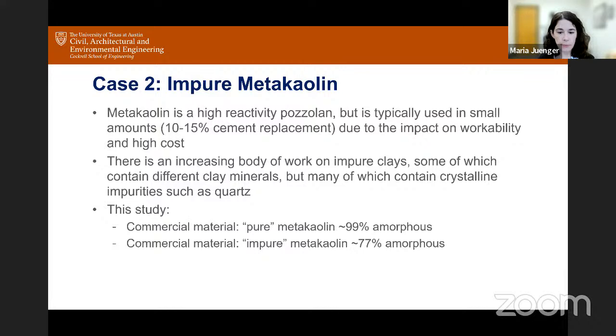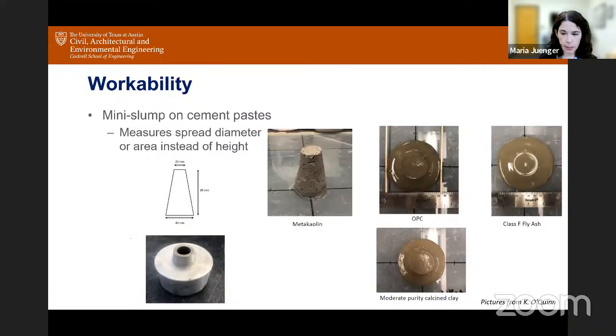The particular example that I'm going to show you today is a commercially available pure metakaolin type material that's compared to an impure metakaolin material that's primarily quartz mixed in with metakaolin. So it's not a reactive material. And you see the difference in amorphous contents there of 99 versus 77%. And I have some other materials I'll show you as well, but in this particular case study, I'm focusing on these.